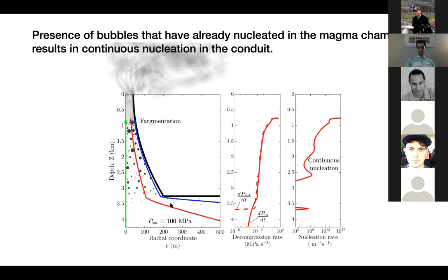The different colors show different path lines of magma in steady conditions. What basically controls nucleation rates in eruptions is the competition between decompression rate, which tends to increase supersaturation pressure and increase nucleation rate, and diffusion rate, which tends to reduce supersaturation pressure and stops nucleation. This competition is shown in this figure. The solid line is the decompression rate. The dashed line is the rate of decrease in saturation pressure of water due to diffusion.